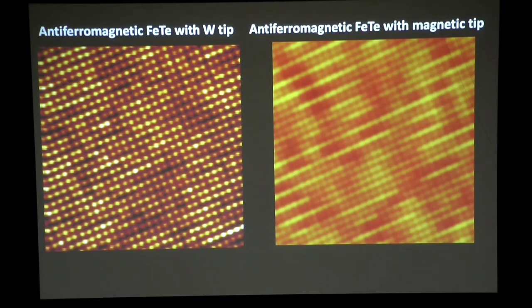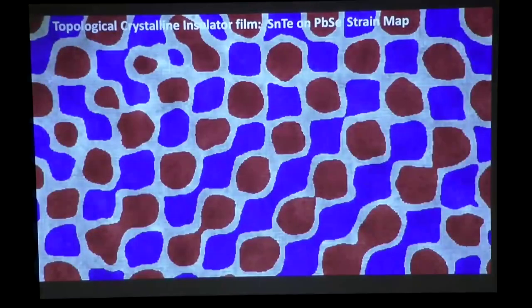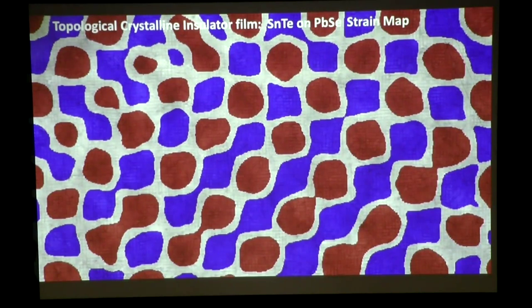The interesting thing about STM is when you do normal STM with a tungsten tip or some metallic tip, you see only the atoms. Here you're measuring the tellurium atoms. But if you use some kind of a magnetic tip, now suddenly you're able to see the stripes resulting from the antiferromagnetism in this compound. So you can image spin at the atomic scale using the STM. You can also measure strain because we have information on where each atom is. We also know how each atom deviates from the position where it should be.